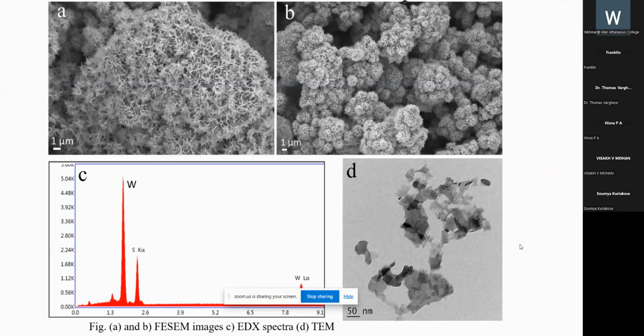Coming to the results and discussion, figure A shows the XRD, B shows the Raman, C shows the band gap analysis, and D shows the FTIR. XRD confirms the hexagonal phase of WS2, and Raman analysis shows two major peaks confirming the in-plane and out-of-plane vibrations of WS2. The band gap of 1.72 eV ensures the presence of few layers of WS2. The BET surface analysis shows the material has a highest surface area of 28 meters squared per gram. Coming to FESEM analysis, A and B show a novel flower-like morphology, and C shows the EDAX spectrum, where the presence of W and S was confirmed. No other impurity phases were observed.